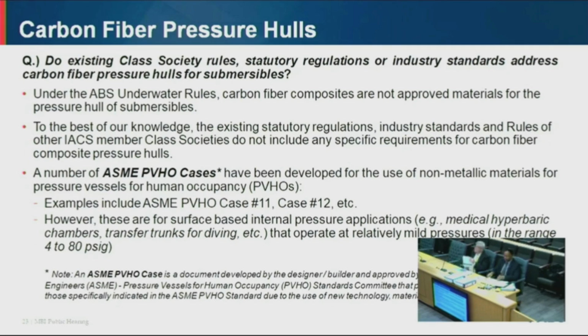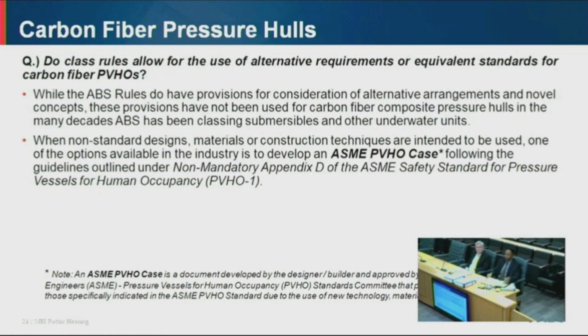Then case number 12 was a non-metallic portable hyperbaric stretcher, and the material used was a liquid crystal polymer tube, which was enclosed in polyurethane and which was then coated with nylon. And the maximum pressure for this application was in the range of 33 to 75 psig. So all of these are for internal pressure applications, and they are for very mild pressures as compared to the pressure at a depth of 4,000 meters seawater. Okay, next.